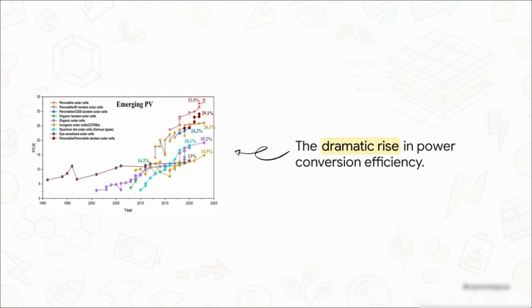And this brilliantly illustrates the hype. The power conversion efficiency of perovskites has just skyrocketed. We're talking a massive leap from a measly 3.8% to an impressive 26.1% in just a few short years. And when you stack them in tandem with silicon, bam! They hit a staggering 33.9%. They are rapidly catching up to, and in some ways surpassing, literally decades of standard silicon research.